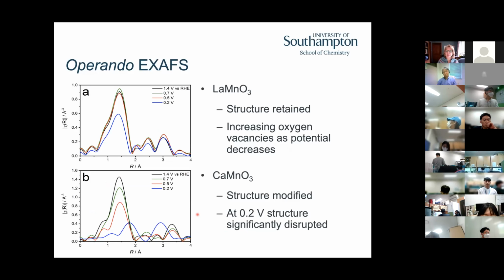And that's reflected in the XAFS spectrum, in the Fourier transforms of the XAFS region. You can see from the lanthanum, as we reduce it, the amplitude of the manganese-oxygen coordination is decreasing, but the overall structure, as reflected in these higher shells, is not changing, right? So I'm not losing my perovskite structure. With the calcium manganate, as you reduce it, because you over-reduce it, you lose that structure. These peaks are really different from those. So we've had some significant structural disruption, right?